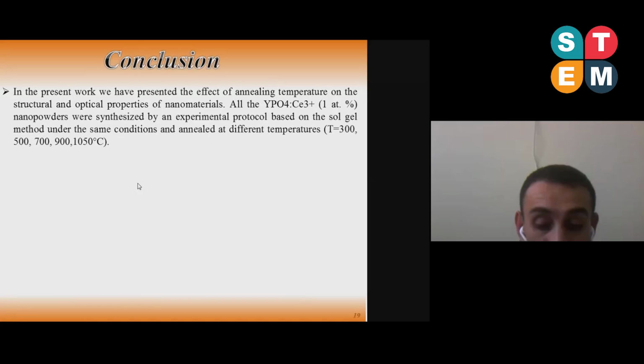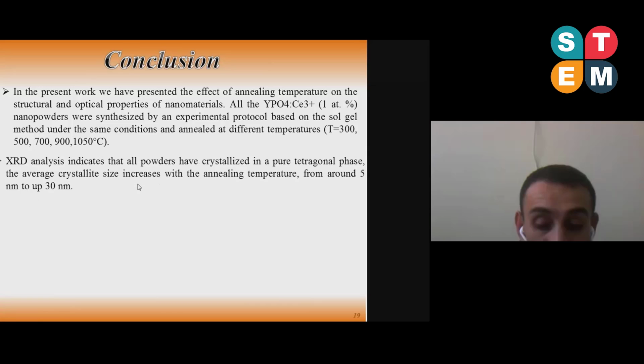In conclusion, in the present work, we have presented the effect of annealing temperature on the structural and optical properties of nanomaterials of yttrium orthophosphate doped by cerium 3+ ion. Nanopowders were synthesized by an experimental protocol based on the sol-gel method under the same conditions and annealed at different temperatures. The analysis indicates that all powders crystallized in pure tetragonal phase. The average crystallite size increases with the annealing temperature from around 5 to 30 nanometers.